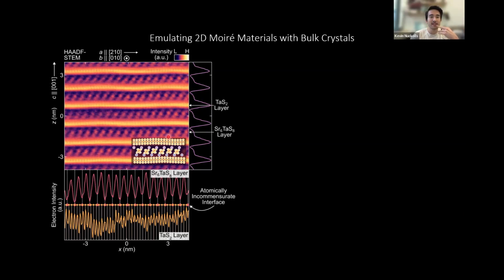The first is if you take a line cut along the spacer layer and you project the intensity of the STEM image, and you take a line cut of the hexagonal layer nearby, and you try to project them against one another, you'll see that they are atomically incommensurate, that this interface is incommensurate in real space, indeed confirming what we saw in X-ray diffraction. The second thing is that because we're cutting through the cross-section of this crystal, we can see this warping of the layers, which is exactly warping with the Moiré wavelength. So this is seeing that the crystal layers are trying to interfacially relax against one another because of the incommensurability, exactly as we see in 2D Moiré materials. So this is a further confirmation that the Moiré superlattice is a dominant scattering vector. It's a dominant energy scale in this crystal formation.